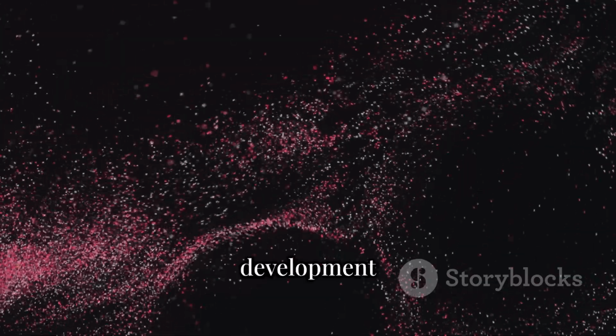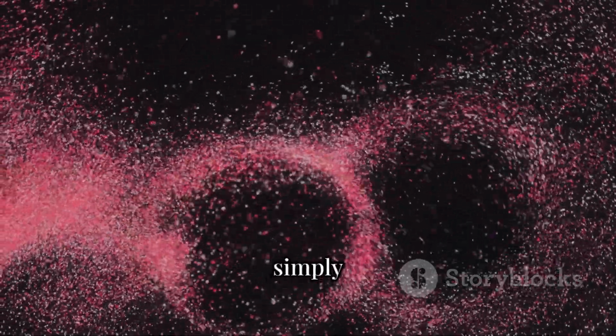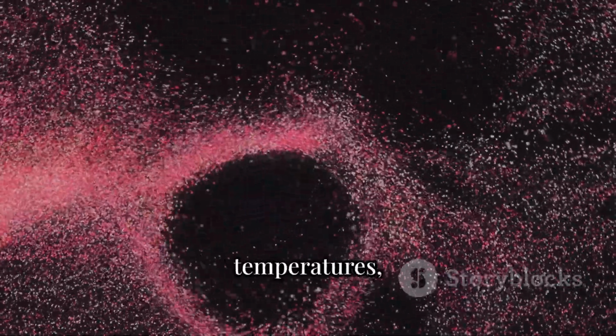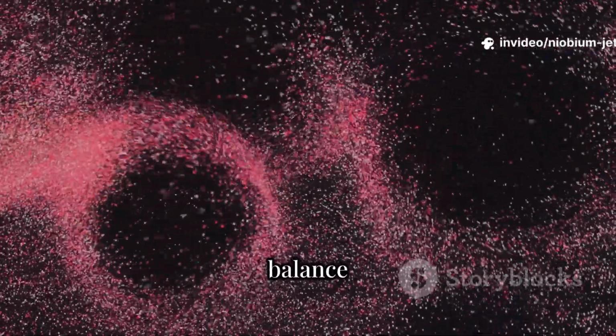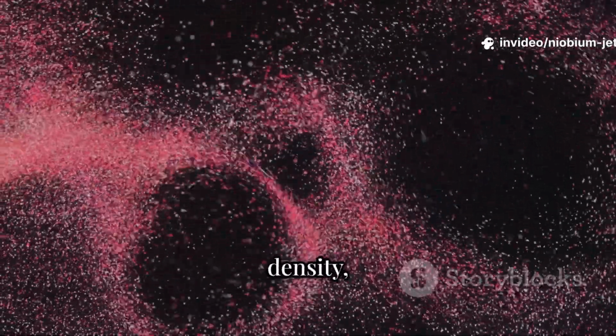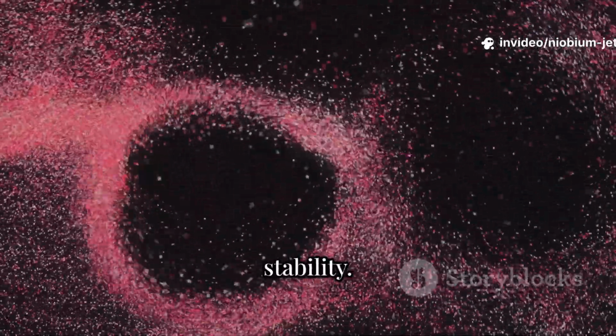This limitation can affect the manufacturability and defect tolerance of components, as brittleness restricts formability and resistance to crack propagation during use. Therefore, the development of niobium alloys is not simply a matter of achieving higher operating temperatures, but of solving an intricate balance between their mechanical properties, density, and long-term environmental stability.